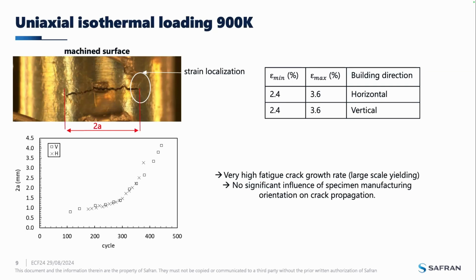Because of this intense loading, as you can see at the crack tips, there is a strain localization. So the crack is measured as illustrated here. And as you can see on the graph, fatigue crack growth is very high, and there is really no significant influence of specimen manufacturing orientation on crack propagation. So the heat treatment is well done.